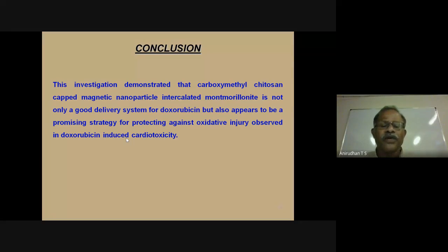So there are two advantages, especially for introducing this doxorubicin, and doxorubicin has a side effect. That side effect may be eliminated after introducing this new material. This is the advantage of this material, and this finding is also published in a very good journal. Because this side effect we can eliminate after using this type of material.